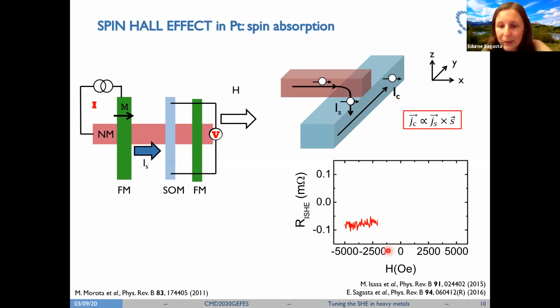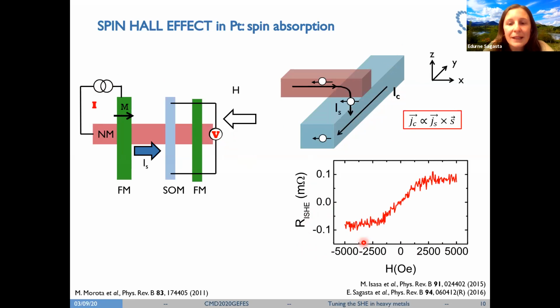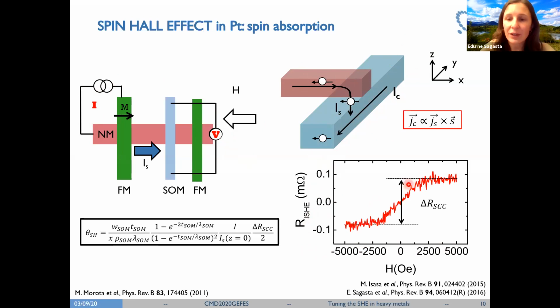Now if we sweep the magnetic field, we will be able to inject spin of the opposite polarity, and therefore the generated charge current will point in the opposite direction, giving rise to the opposite resistance. From the difference in the resistance value, we extract the spin to charge conversion signal, and by using this equation, where we have to consider the amount of spins that have been absorbed in the spin orbit metal, we are able to extract the spin Hall angle value.